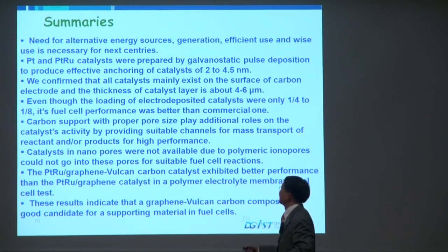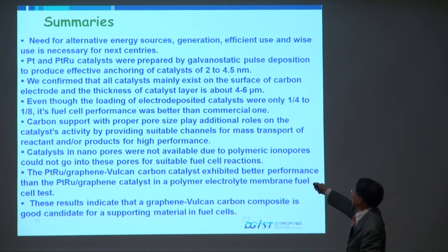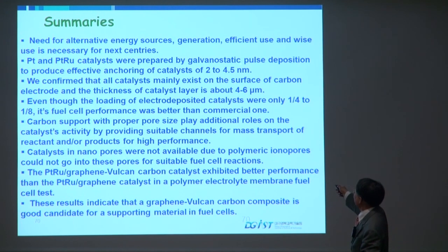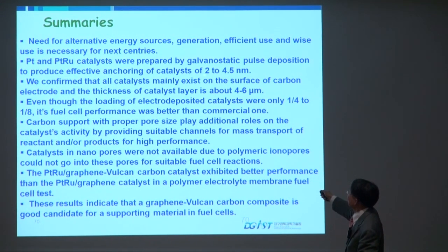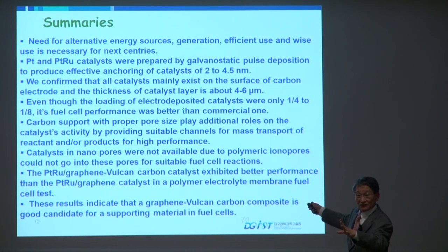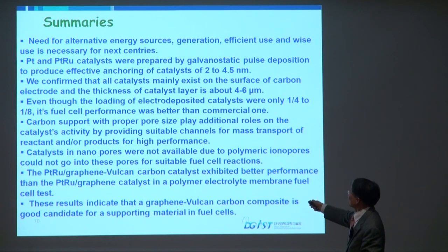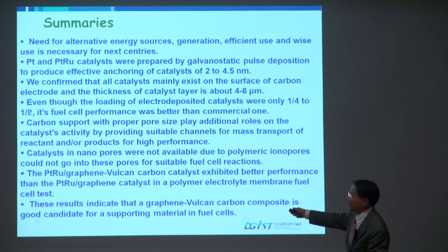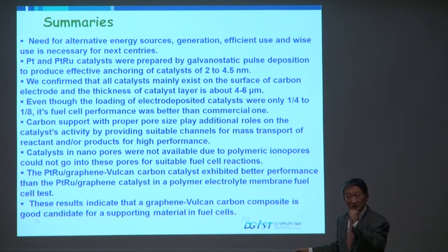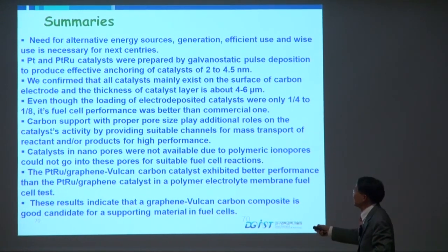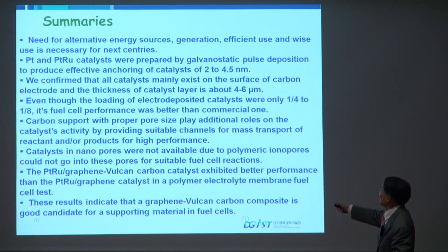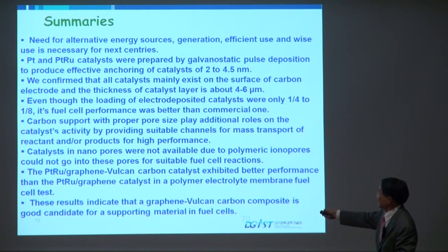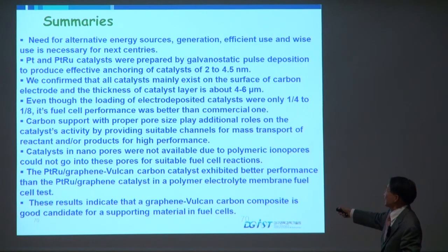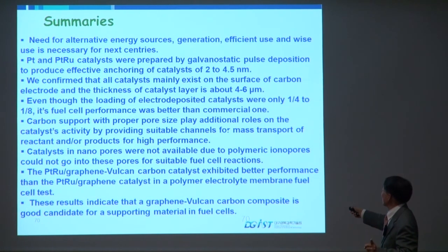And in summary, the need for alternative energies. Platinum ruthenium catalyst prepared by galvanostatic deposition method, and the catalyst mainly stays on the surface of it. And the loading is only 1/4 to 1/8. The performance turned out to be even comparable or even better. And carbon support with proper pore size plays an additional role in the catalyst's activity by providing suitable channels for mass transport.